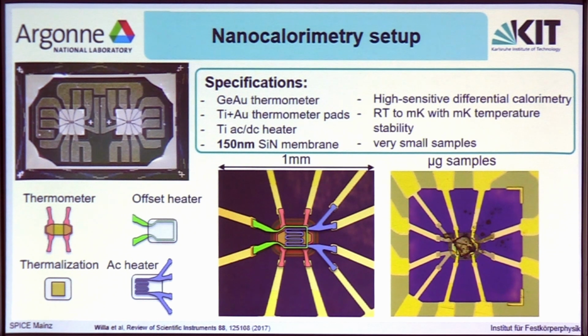And since we're using the AC specific heat technique, what we actually need is an AC heater, which subjects our sample to an oscillatory heat current, and we then pick up the second harmonic response of the sample via a thermometer. The offset heater here is used for regulating the overall temperature of our sample. So since the thin membrane has a very low thermal conductivity, it actually decouples our sample from the environment, and as it itself also has a very low heat capacity, it adds a very low addenda to our measured specific heat. And with this, we are actually able to measure very small samples, easily smaller than 50 by 50 by 10 micrometers or microgram in size, to a very high resolution.